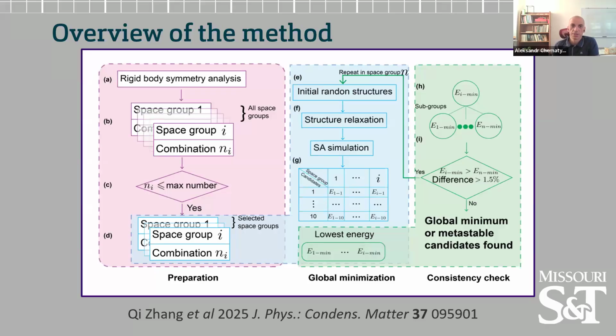And then we start to count how many different possibilities, how many different permutations, how many different combinations we have of placing atoms that we have in our system, usually metallic atoms, and rigid bodies into a particular setting of the particular space group. And for some space groups, as we will see in a moment, there are so many possible combinations that it isn't practical, and this is one of the stumbling blocks in this direction. So we will limit ourselves to some max number to be practical, and within these selected space groups, we will run all possible combinations of the arrangements of atoms and rigid blocks among the Wyckoff positions.